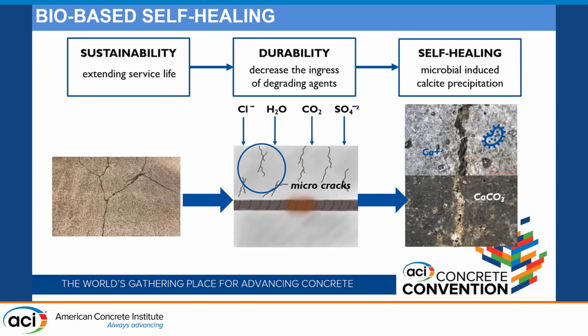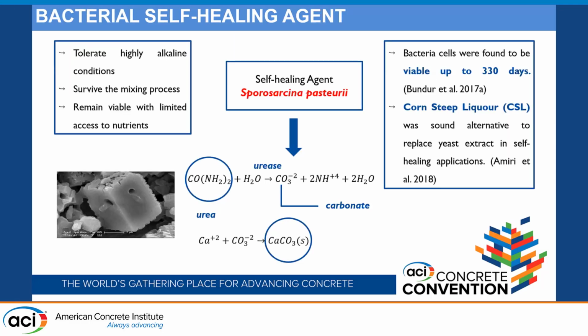In order to preserve the durability of the concrete, instead of traditional cement-based repair methods, sustainable self-healing methods can be applied. Microbial-induced calcite precipitation is a promising technology to remediate microcracking in concrete and decrease the ingress of detrimental components. To provide a self-healing mechanism through microbial-induced calcite precipitation, it is required to select a suitable bacterial culture and incorporate the cells with the corresponding nutrients to create a proper environment for crack closure. Therefore, the main challenge of the application is finding microorganisms that can tolerate the highly alkaline conditions of the cement paste, can survive the mixing process, and can remain viable with limited access to nutrients.